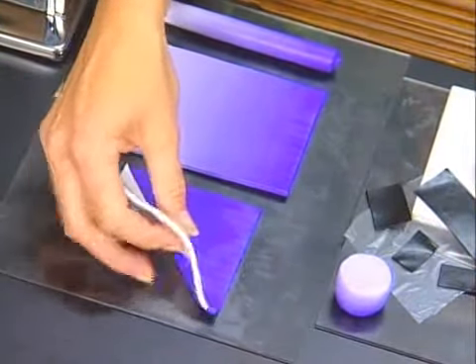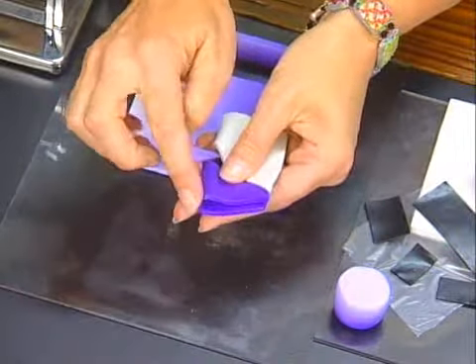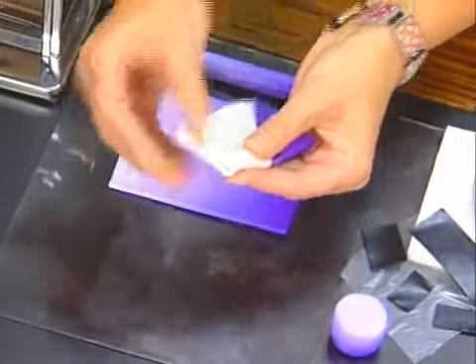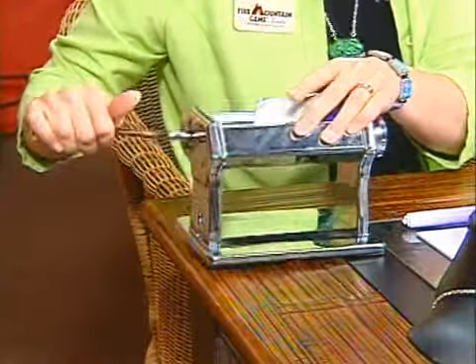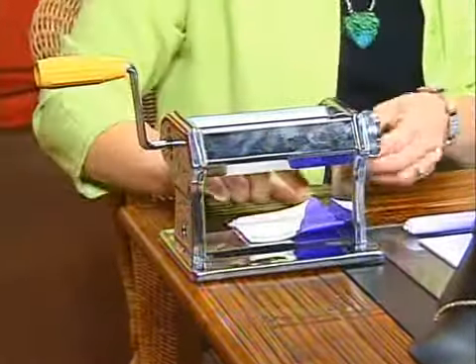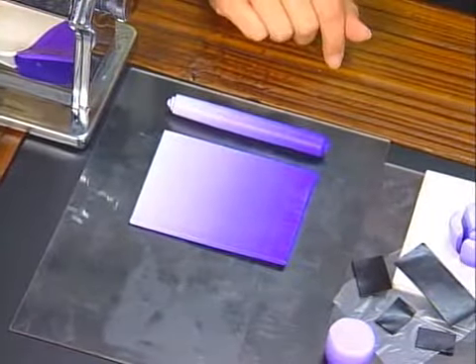We're going to pick it up — it's two right triangles reformed into a square. When you fold it in half, make sure that the violet edges touch, so the like pieces touch. And the white edges touch. We're going to put it in our pasta machine, fold side down, because we don't want any air in the clay. You do need to condition polymer clay, so roll it through the pasta machine. After about 20 times, you'll get a gorgeous blended sheet that just blends the colors together. You continue folding and rolling, just like that, about 20 times.